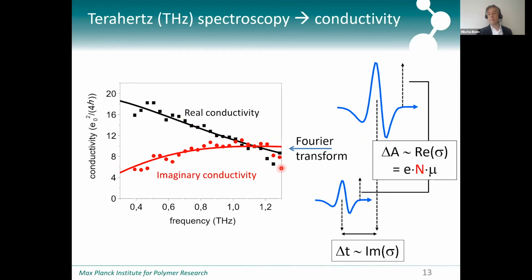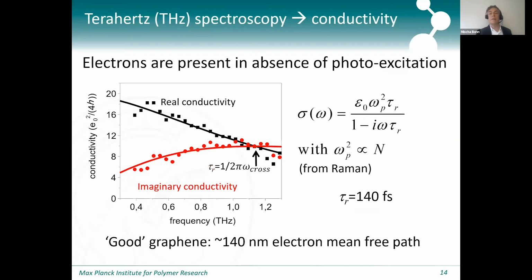So we have this rather large range of frequency over which we can determine the frequency dependent real and imaginary conductivity. And the lines that you see here, this black line and the red line, are a fit description of the data using the Drude model. And the Drude model is a standard textbook model of electrons that move around in a material, and they scatter every now and then, and that every now and then is determined by this tau r, the scattering time, due to phonons or defects or other charge carriers. And you see that this simple model describes the data remarkably well, with actually only one free parameter, which is the scattering time. So the density of the charge carriers, which determines this plasma frequency, this we can obtain independently from Raman measurements.